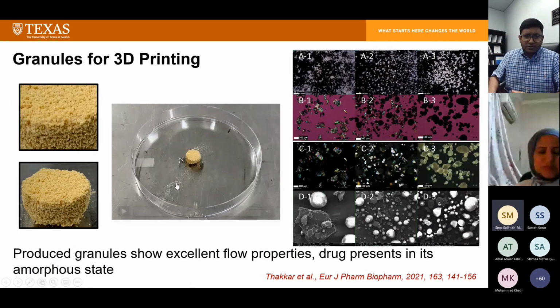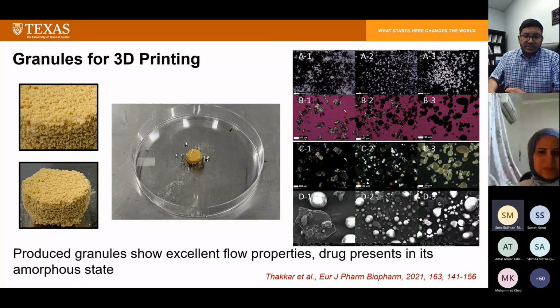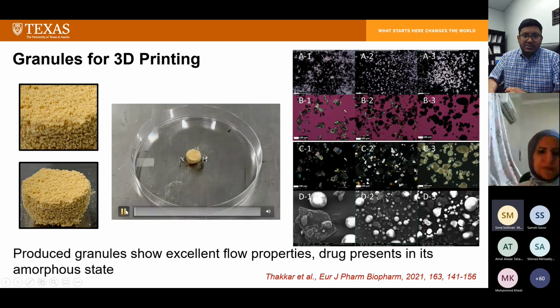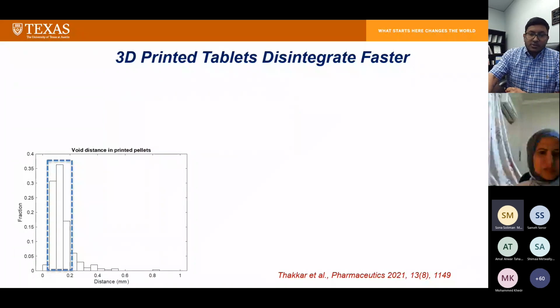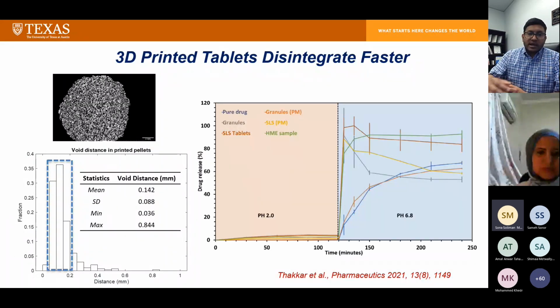This is just a short video to show, once the tablets are printed, how fast they disintegrate, because the faster disintegration is due to the porosity of the tablets that we produce through the laser sintering process. These tablets disintegrate within about 3 seconds without any agitation. The moment you introduce water, it disintegrates. The reason is that the tablets we produce are highly porous, and the mean value of the void structure is about 142 micrometers.